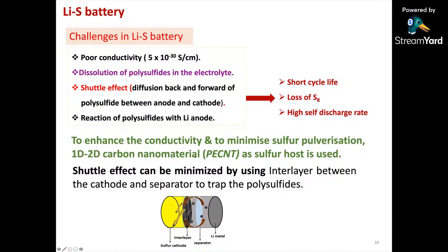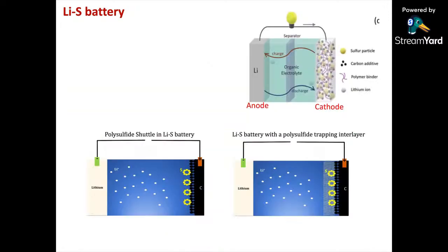1D-2D carbon nanomaterial. Why do we use 1D, 2D? One-dimensional carbon nanotubes have excellent electrical conductivity, but the specific surface area is very low. Whereas in the case of two-dimensional graphene, because of the synthesis process, the electrical conductivity is very low when compared to carbon nanotubes, whereas the specific surface area is very large. So what we have done is 1D, 2D carbon nanomaterials, where we have taken carbon nanotubes and cut open only a few of the layers, just a few of the layers.